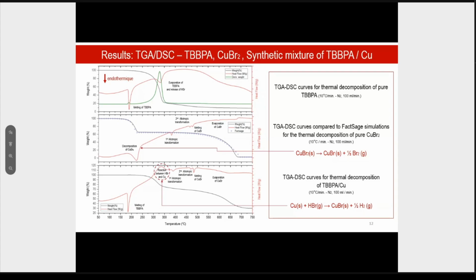So the second graph shows the thermal degradation of copper(II) bromide that we just mentioned, simulated using FactSage. Now we are comparing what we simulated using FactSage in an open system to our experimental test using TGA and DSC. As you can see, FactSage is able to predict the thermal degradation of pure brominated metals, since we can see the decomposition of copper(II) bromide followed by two allotropic transformations, the melting and the evaporation of copper bromide.